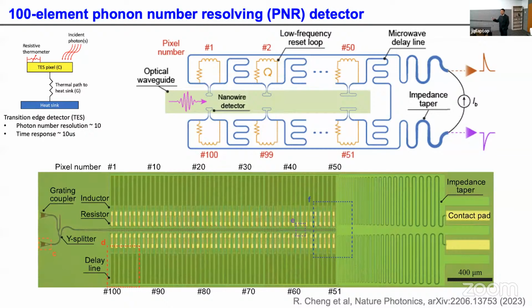If you're familiar with photon number resolving detectors, there's a commercial solution, for example transition edge detectors. Basically, they are bolometers that work at millikelvin, and you can detect up to 10 photons with very high efficiency. The drawback is that the speed is relatively slow, because under that temperature the thermal conductivity goes down, and the response time is normally 10 microseconds. Our nanowire detector aims to solve this problem by providing large photon number detection and also achieving high speed.